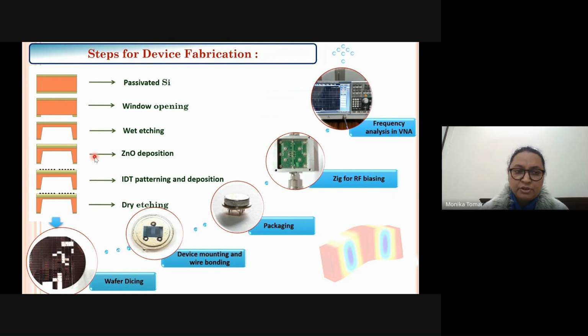Then onto the membrane, we deposit the zinc oxide thin film. On the zinc oxide thin film, we do the IDT patterning, and then we do further dry etching so that the thickness of this membrane is further reduced and we get the membrane thickness of appropriate size.